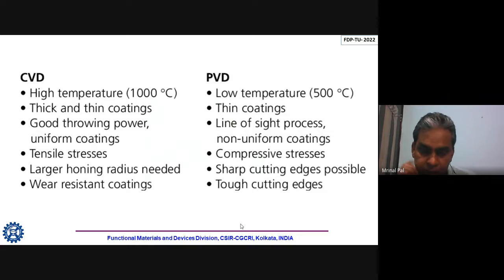Now grossly, CVD versus PVD. I have mentioned everything earlier, but in a single slide you can see the difference. So CVD is a high temperature process, whereas PVD is a low temperature process. In case of CVD you can end up with a thick film, but in case of PVD you can get thin film and ultra thin film. In case of CVD, uniformity is very good, as throwing power is very good, but for PVD uniformity is not that good. In CVD, as it is at high temperature, generally tensile stress grows, but for PVD generally compressive stress grows.